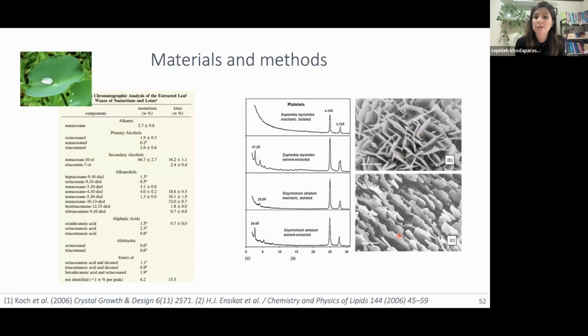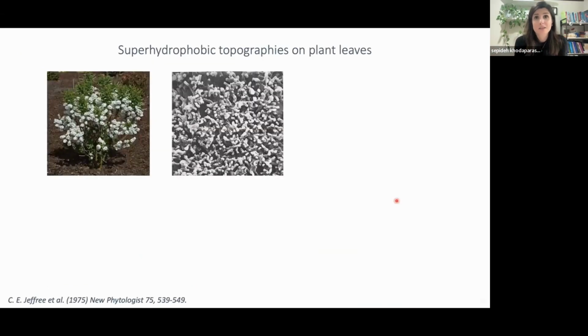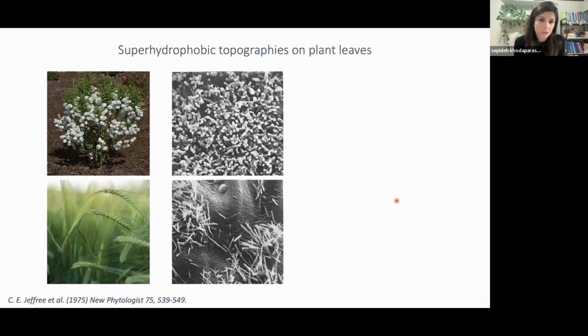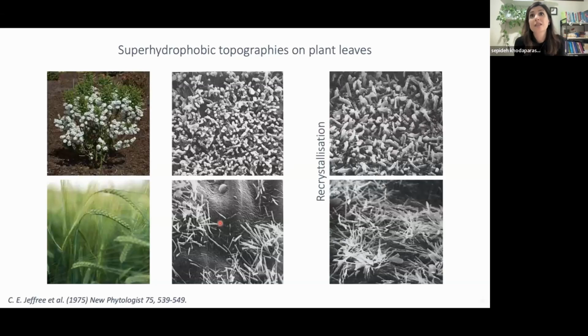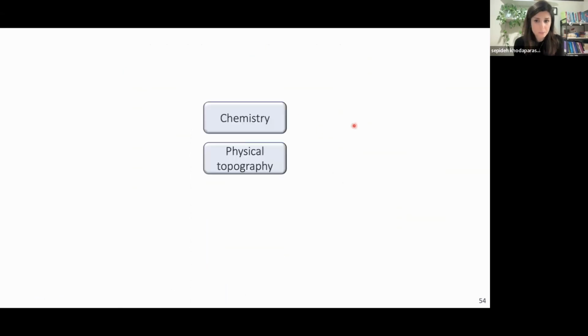So already looking at these crystals, that's where the whole idea that we had about crystallization came from. Crystallization is a really good technique for creating small scale surface pattern over larger scale areas. And in fact, from the 1960s, 1970s, plant biologists knew that these are crystalline structures. From the start of the electron microscopy days, they looked at the crystal structures on different leaves of plants, and they tried to extract the wax and recrystallize it. Depending on the plant, they got quite similar structures. So we know that the chemistry and the physical topography in nature are linked in most cases.